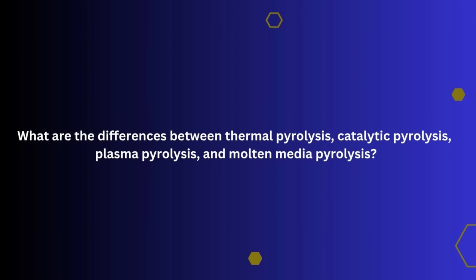Yes, thank you. So methane pyrolysis is fundamentally a so-called endothermic process, which means that it requires heat to happen. And high temperature heat drives the decomposition reaction. And typically, if you don't use a catalyst, I'll get back to that later, you need temperatures above 1200 degrees Celsius, even up to 1400. And then you have the environmental conditions to crack the methane. Now, if you add a catalyst, that actually reduces the required temperatures and is hence more energy and cost efficient. And people have been studying a range of catalyst materials. Nickel-based catalysts are among the most common and extensively studied because they demonstrate good activity at moderate temperatures.